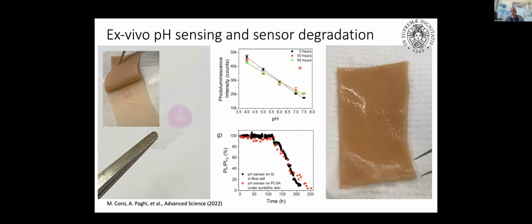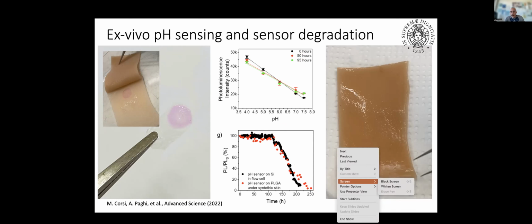The calibration curves don't change significantly over time until 100 hours. And then after roughly 100 hours, the silicon scaffold starts to degrade and disappear. And here you can see a nice demonstration of this.